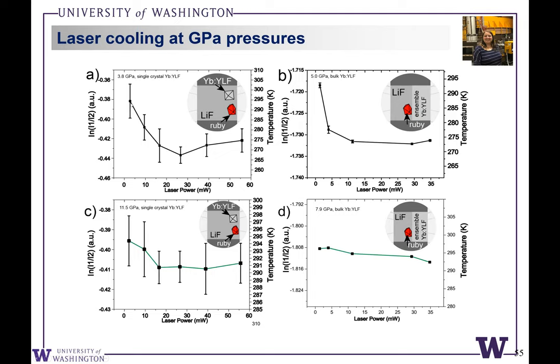And we can then measure the temperature of the yttrium lithium fluoride grains as a function of laser excitation power. And we can see as we increase the laser power, the blue to red ratio starts to go down. In terms of a Boltzmann fit, that's effectively telling us that there are fewer blue photons emitted than red photons, and that correlates with a cooling trend in the temperature. We see a saturation effect where at a certain laser power, we stop cooling and we start heating again.